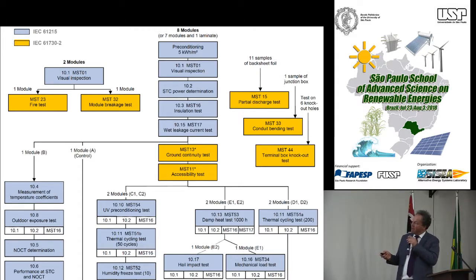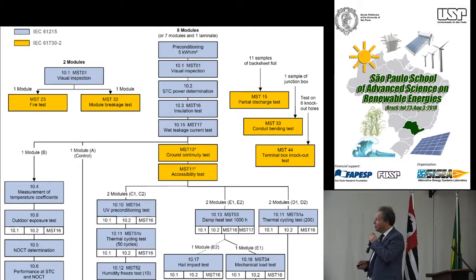Also, you have the damp heat test. For example, here it goes to 1,000 hours, kind of a sauna at 85 degrees Celsius, but at a very high humidity, at 85% humidity. And 1,000 hours is 1.5 months. Many modules fail there, and you can check that by doing visual inspection and power output. Very often the leakage current is too high.